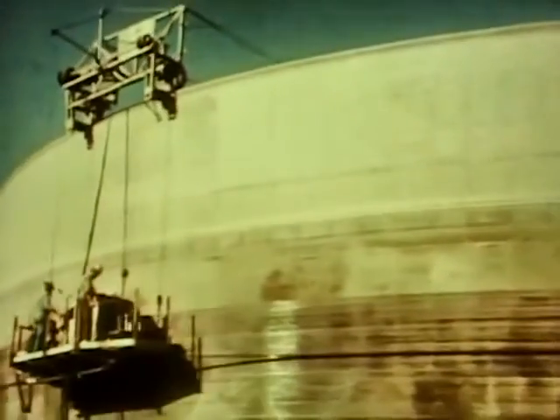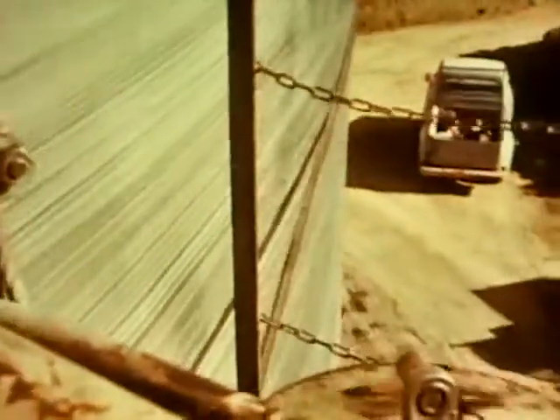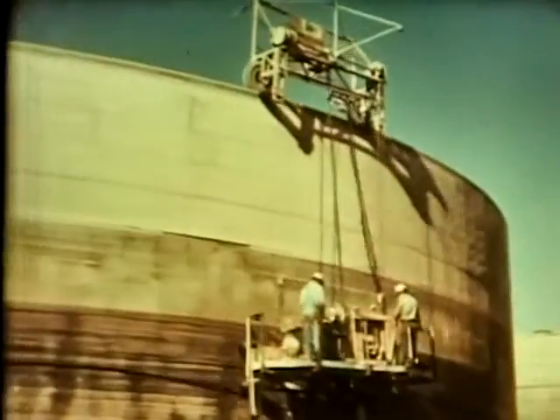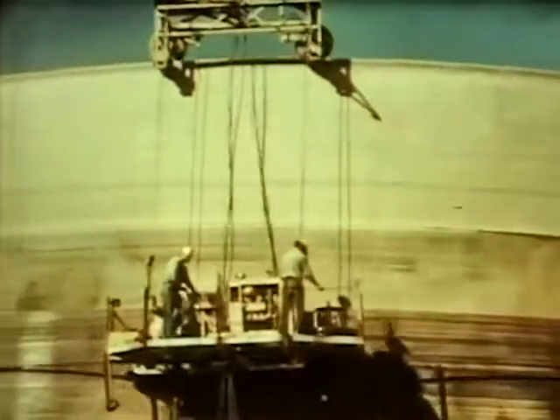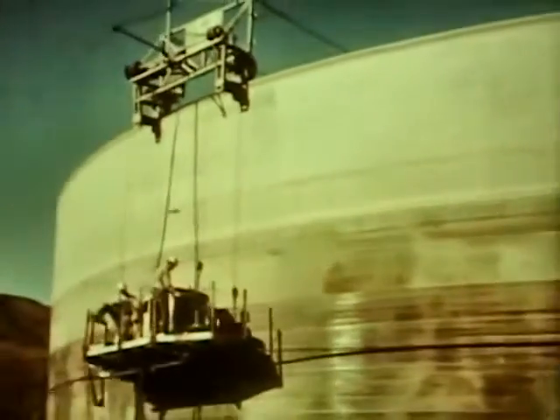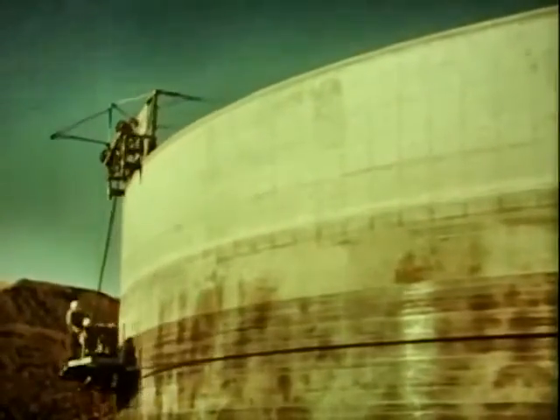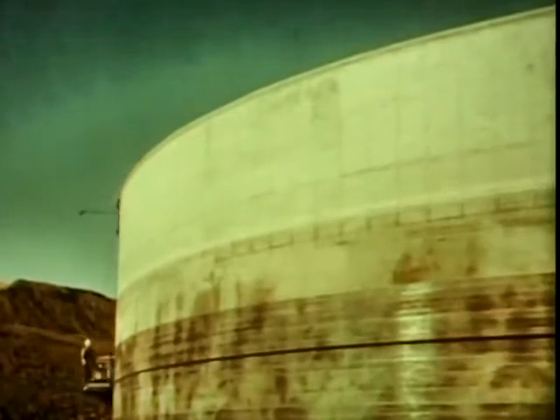In the preload winding operation, the stressing of the wire is achieved by drawing it through the die. The wire is laid in its proper position on the core wall under accurate initial stress of 150,000 pounds per square inch. The machine is self-propelled and operates at speeds up to 8 miles an hour through sprockets which engage an endless chain around the tank.